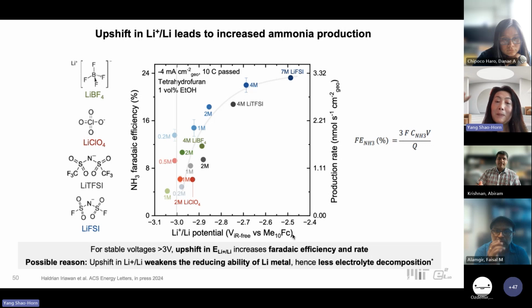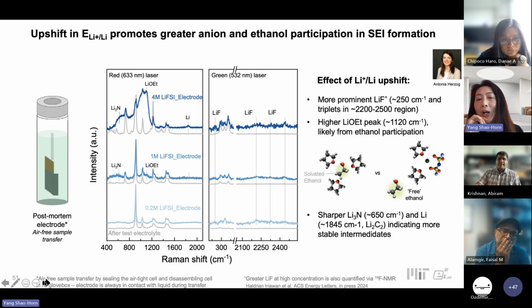On a solvent-independent reference, the lithium redox potential can be tuned by, let's say, 0.6 volt, and you can also see the Faraday efficiency can be increased significantly as we change the redox potential. And this has to do, we believe, through in situ Raman measurements, with forming a more pronounced lithium fluoride, and more pronounced reaction intermediates, such as lithium alkoxide, and a more crystalline lithium nitride.